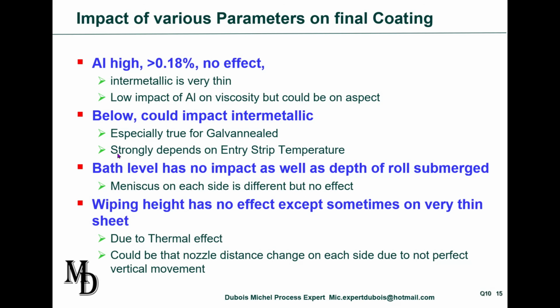Galvanneal is also different. I'm talking here about galvanizing. Of course, below 0.18 the situation could be different, and it also depends on the entry strip temperature, because in that case we make an intermetallic, and that intermetallic can be thicker. And this is already a solidified piece, so it means it cannot be wiped.